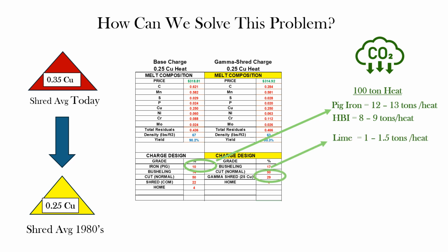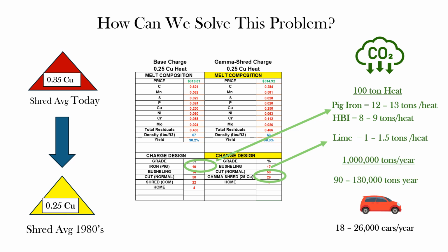Moreover, since we're putting in a much cleaner grade of shredded with a higher yield and lower contamination level, we're able to reduce the lime, burnt lime in the charge, and the equivalent of 1 to 1.5 tons of CO2 reduction per heat as well. This doesn't sound like a lot until you scale it up to a 1 million tons per year steel mill, and you've got a 90 to 130,000 ton reduction in CO2 emission, or the equivalent of removing 18 to 26,000 internal combustion cars from the road per year.